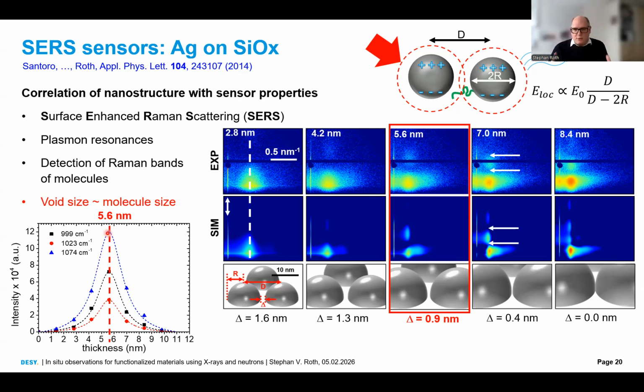And the question was, why? And the reason is here in the structure. If you imagine this triangular structure of hemispheres, the distance d gives rise to this side peak. Between the clusters we have a void size, delta, and we can calculate this void size. It's basically distance minus 2 times the radius. And you see that this void size decreases. So you can say, well, here clusters are far apart, and here the clusters touch each other.